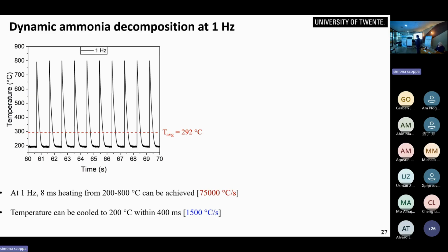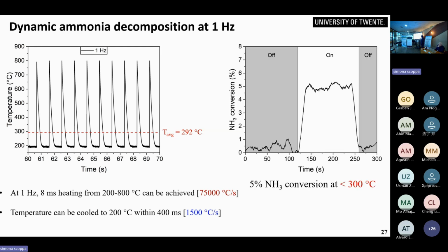So we start running this at 1 Hertz. We send a pulse every second, and we look with a mass spec at what happens with the ammonia. When you have the system off, nothing happens. There is no ammonia breakup. There is no hydrogen. And the moment we turn it on, all of a sudden you see ammonia conversion. We get about 5% conversion at 293 degrees C.